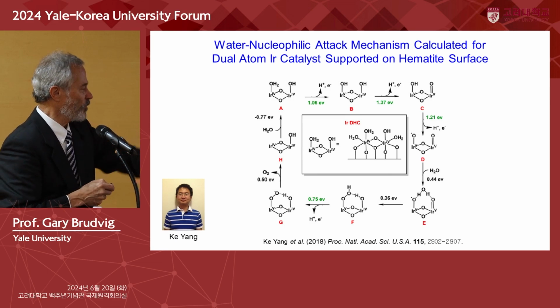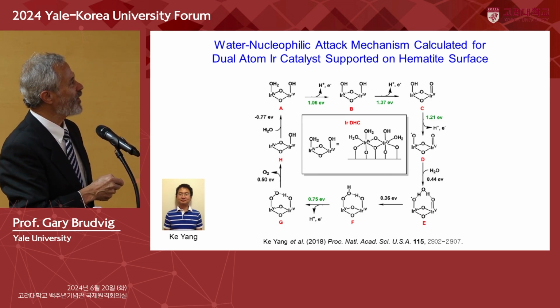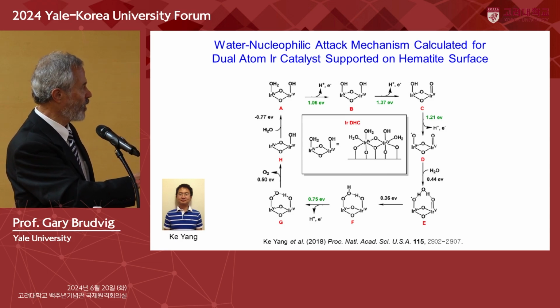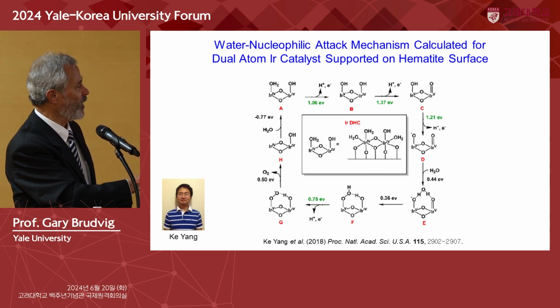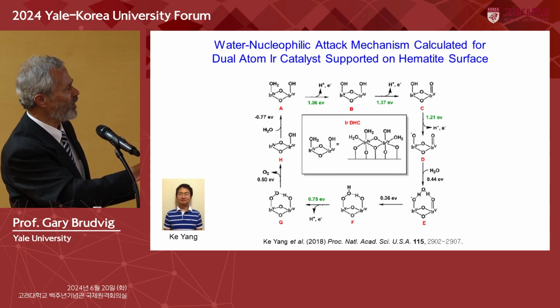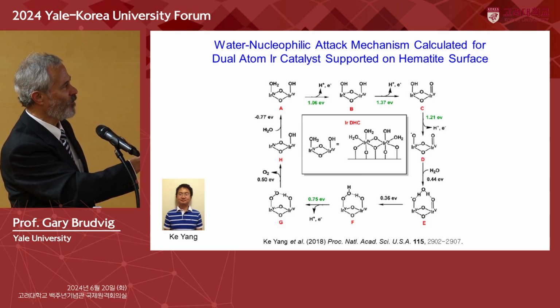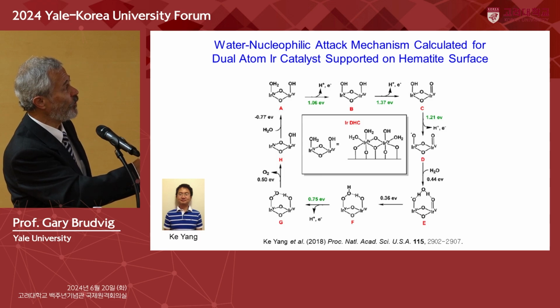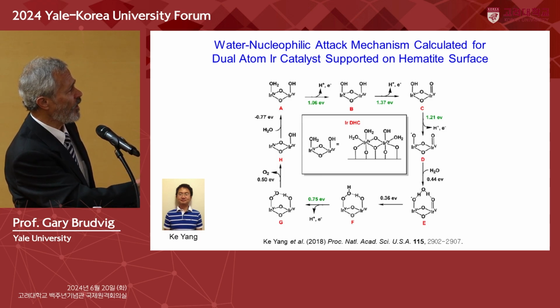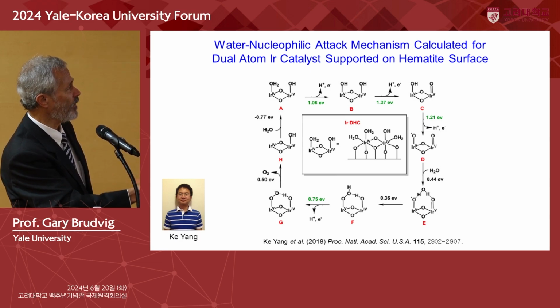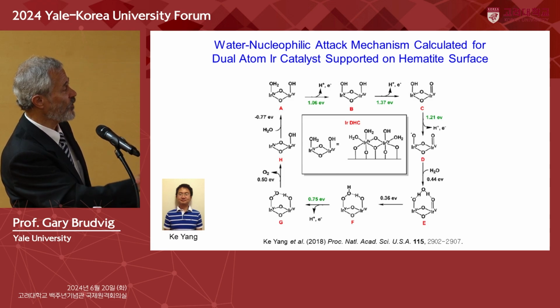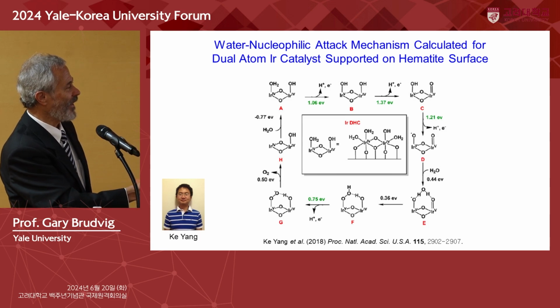You might ask about the mechanism. So this is a computational mechanism by a postdoc from Victor Batista's group, Ke Yang, and he computationally modeled this iridium catalyst on the surface of hematite. And based on the computational model, we proposed a mechanism that involves sequentially oxidizing the iridium ions up to a high oxidation state of iridium 5, which then enables water to attack through what's referred to as a water nucleophilic mechanism. The water forms an attack to form an O-O bond, which then with the fourth oxidation is releasing oxygen. So that is a computational model.